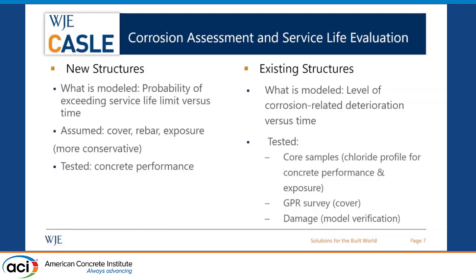For existing structures, on the other hand, we model the percentage of corrosion-related damage and how that increases with time. We rely on field investigation for our input parameters. Typically we collect core samples and look at chloride profiles, and based on that, we can define our concrete properties and exposure conditions. We do a GPR survey, and based on that, we define our cover distribution. We verify our model by comparing the current damage levels to what was predicted in our model, and we can calibrate our assumptions based on that. We have validated our approach through lots of projects.